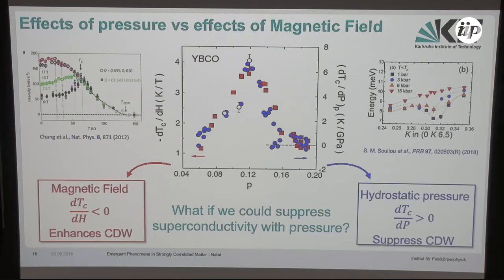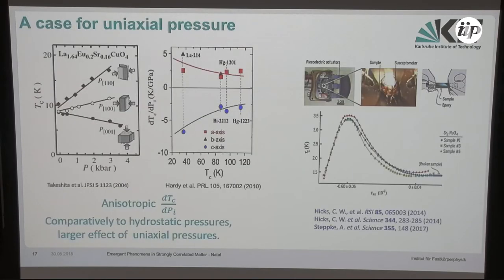Well, it's been known for quite some time that in the cuprates, the critical temperature has a much stronger dependence on uniaxial pressure than on hydrostatic pressure. So this was found in a whole series of cuprates. And actually, there was a lot of work done also in Karlsruhe. I think some of these earlier results, the first time it was observed, was in the PhD thesis of Christoph Meingast. But this was all done in the very low pressure limit.